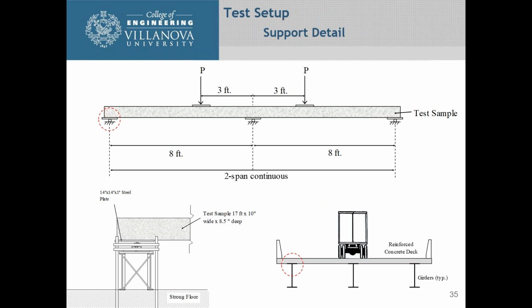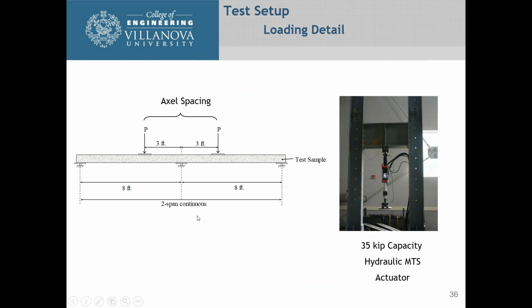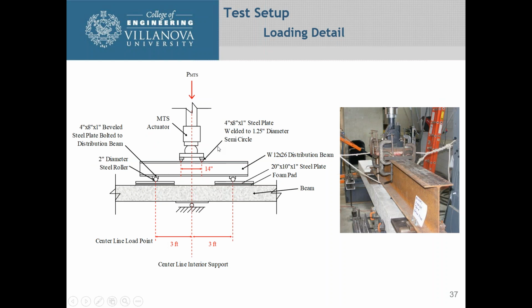So let's take a look at how we set everything up. This is the test setup that we use. There's a concrete sample. We have 2 loads at 6 feet apart, 8-foot spans, and down at the bottom left-hand corner, you can see the sample that we had, and it sat on steel plates that had underneath them load cells, and then we had steel supports to support the ends of it. And you'll see some pictures down the road. On the right, you can see the actuator that we used. It was a 35 kip hydraulic actuator, and it had a plate down at the bottom of it that was attached to a steel beam that distributed the load in 6 feet to the 2 beams.